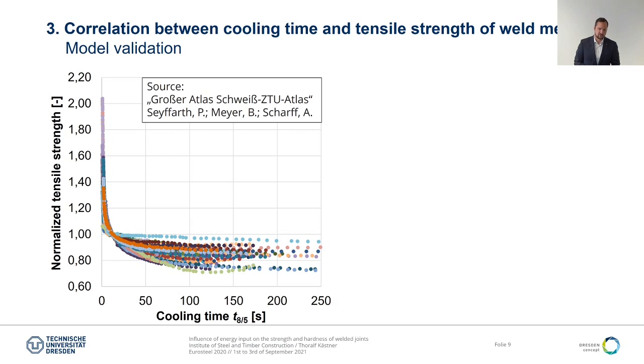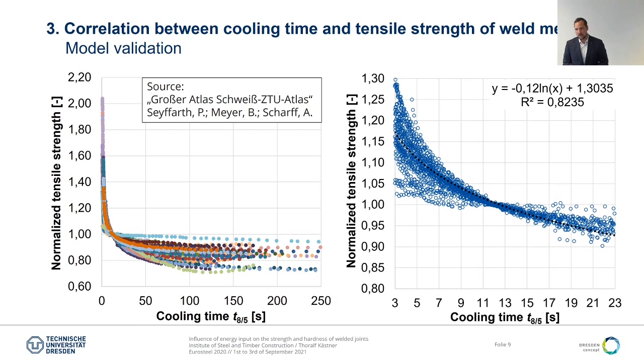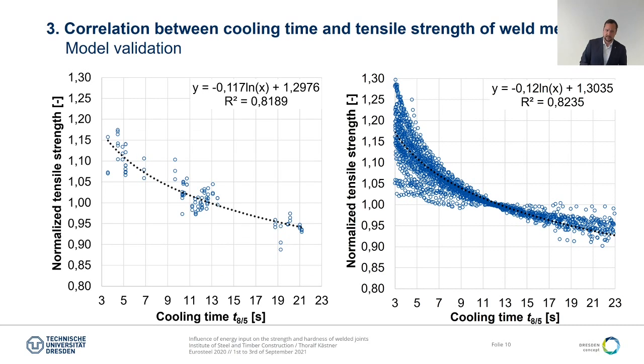You can see the source in the right corner, and having a closer look at our time period of the cooling time, we can see that we have again a more or less comparable correlation to our results. So again, you can see them here, and also the regression function is more or less equal. So we can see that the results we achieved are representative for a huge amount of filler metals.